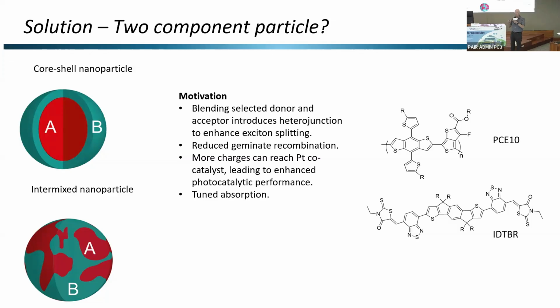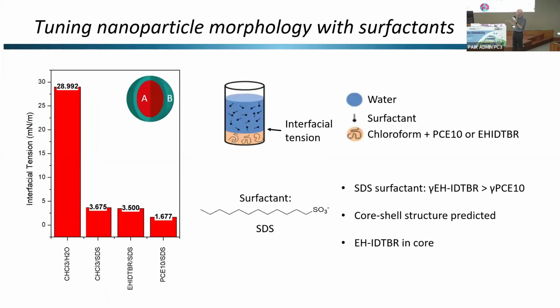The other, of course, is if the two phases just randomly separate into what we call an intermixed nanoparticle. So I'd been working on a bunch of non-fullerene acceptors. This is one from our lab here, IDTBR, and we thought we'd combine them with a typical organic solar cell donor. We're not trying to reinvent anything here. We're just basically taking materials that exist already in a solar cell application and seeing if they work in a nanoparticle. So the way that we make these nanoparticles is the so-called mini emulsion technique.